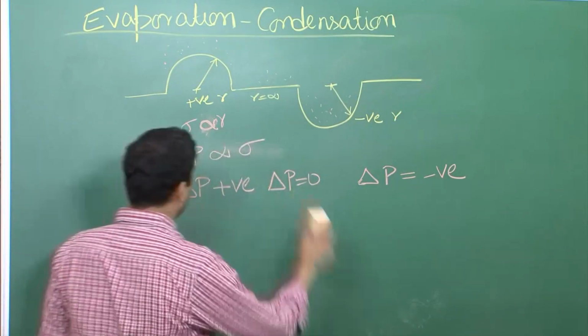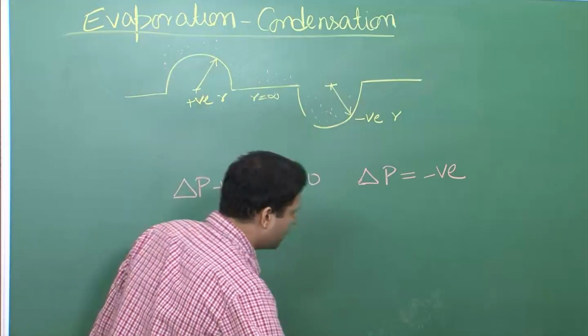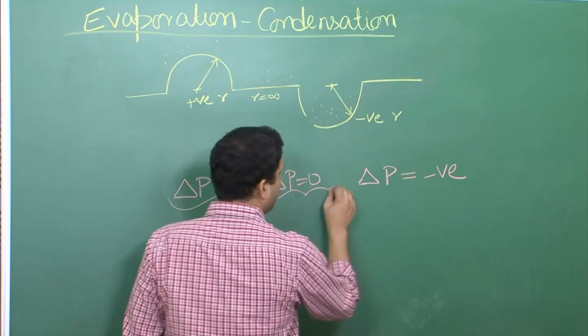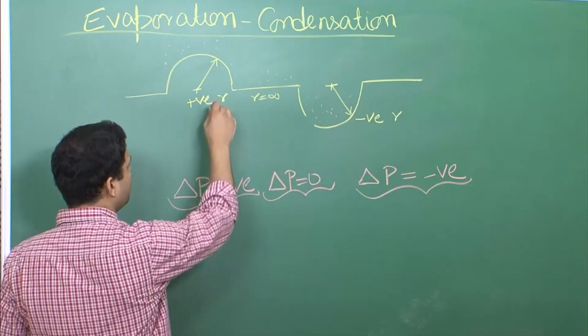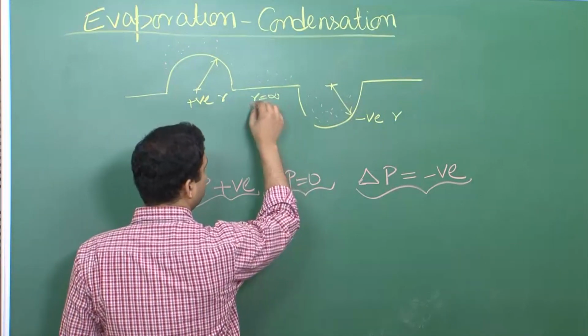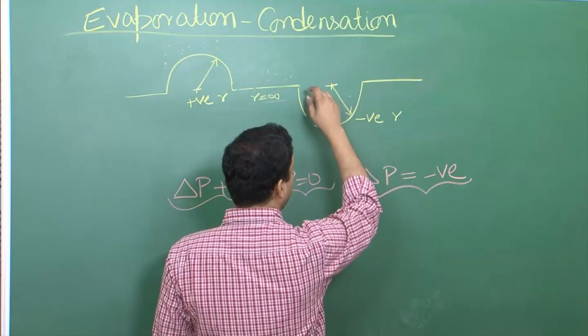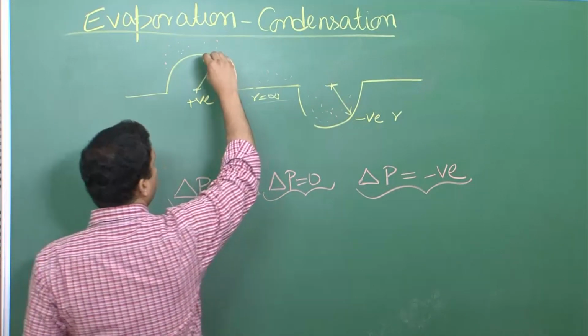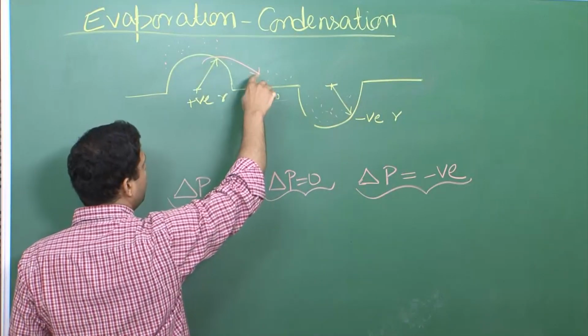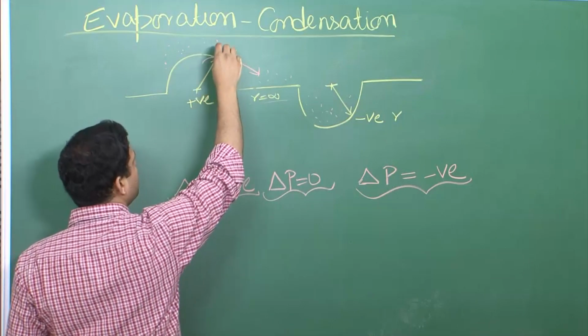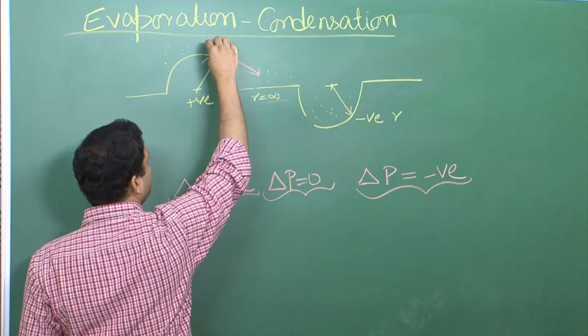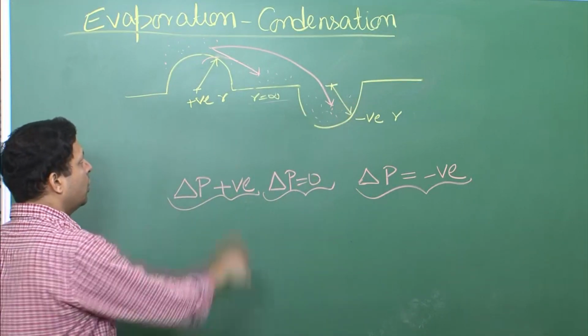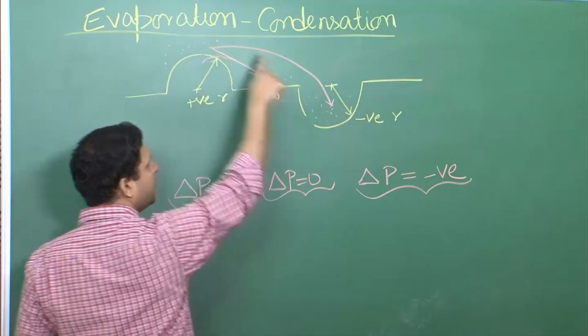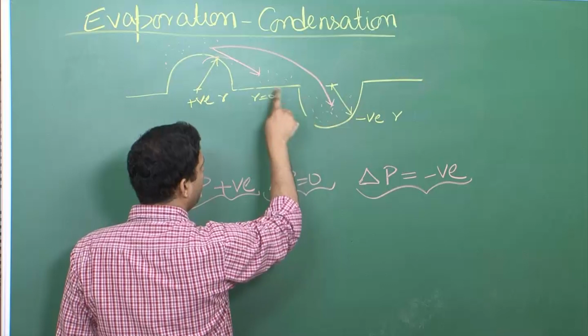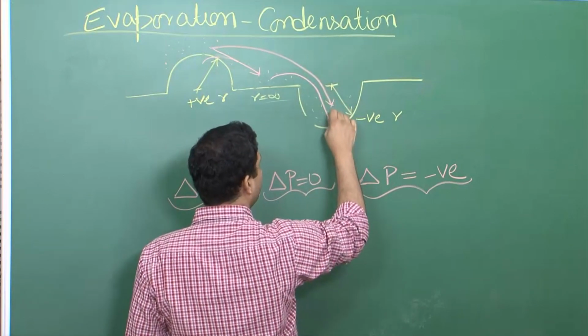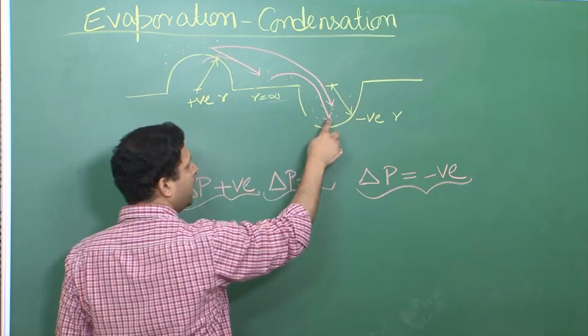In fact, we can forget about this region; it will be better if we just look at how delta p varies with the radius. So, delta p is positive when you have positive radius, delta p is 0 because we are comparing it with the flat region, and delta p is negative when you have a negative radius of curvature. What would that mean? That would mean that material will have a tendency to evaporate from over here and then condense over here, evaporate here and then condense over here. Similarly, this is still negative compared to this. Therefore, again the particles will have a tendency to evaporate from this region and then condense over this region.